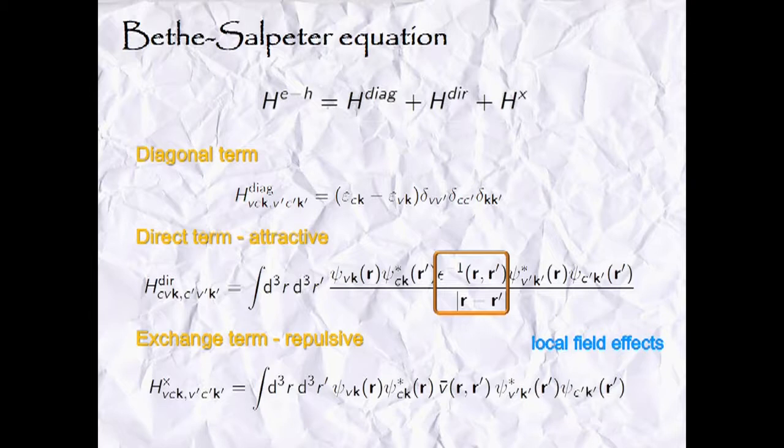Here, the electron-hole interaction is screened. And this gets me back to the questions I've been asking you. So think about in which of these materials the screening is most or least effective. In metals, we have very high electron densities, and that's why the dielectric function is pretty high. So metals will be perfectly screened, and in metals you can more or less safely forget about the electron-hole interaction.